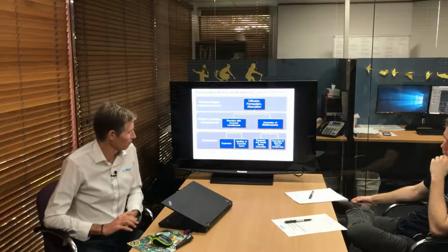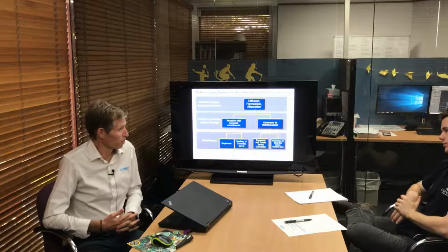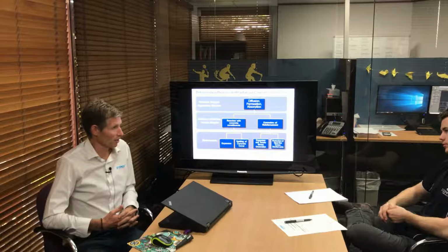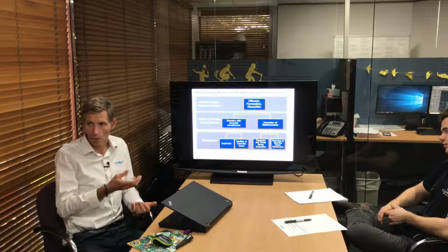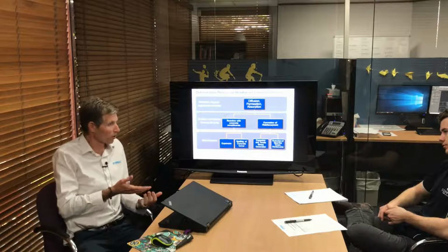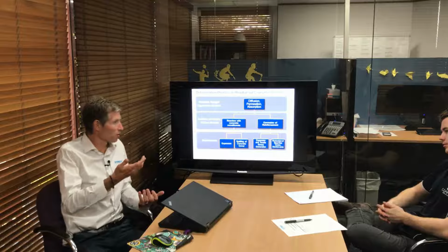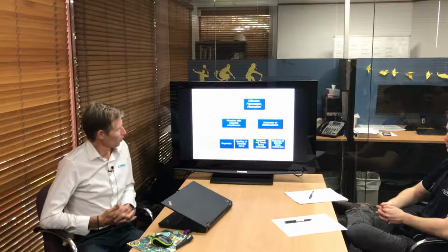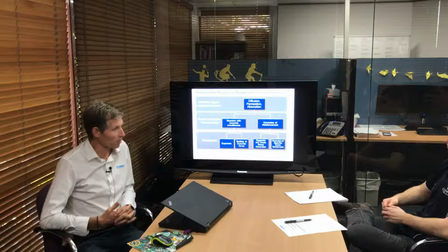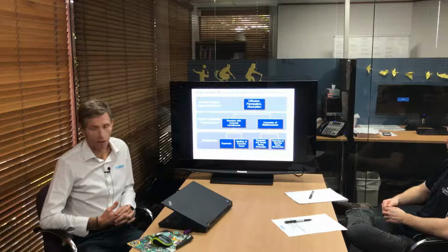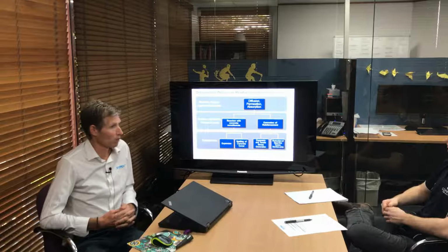So in relation to carbonation, what that is essentially doing is reducing the pH level within the concrete, which means the reinforcement, which is normally encased in a high alkaline environment, becomes under threat as the chemical composition changes within the concrete, which means it starts the process of corrosion relatively early. With chloride ion attack, that's a bit more of an electrochemical reaction that takes place. And once again, that passive layer around the rebar is under threat, and you get the onset of corrosion of the rebar.